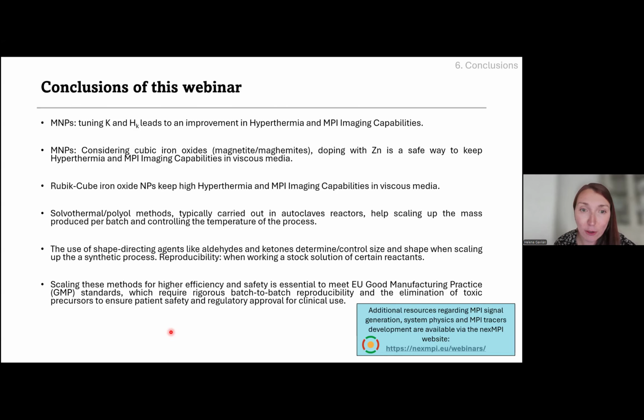So it is, of course, essential to add some molecules that will control the size and that will coat the nanoparticles during the synthesis. This is why in thermal decomposition you add oleic acid or decanoic acid. In the case of the solvothermal as well, you add oleic acid. You can add others, of course. But yes, I believe it is really important to add, besides the shape directing agent, something that will bind the surface of your nanoparticle during the synthesis.